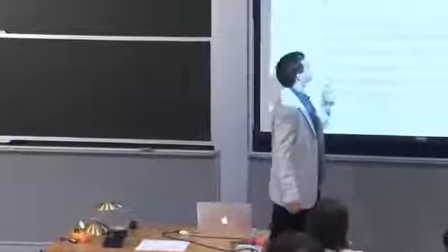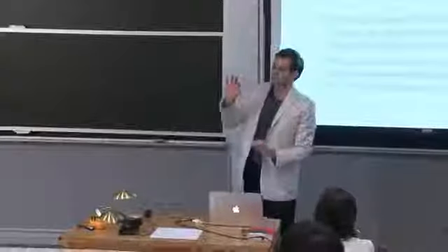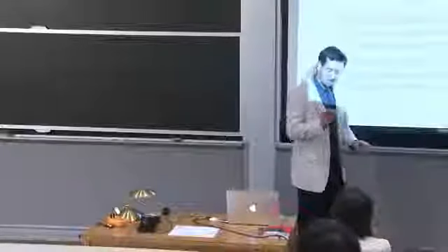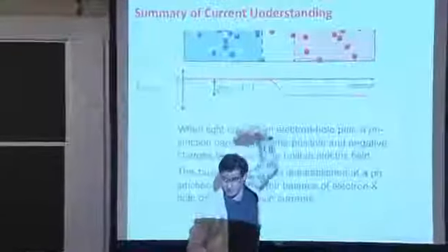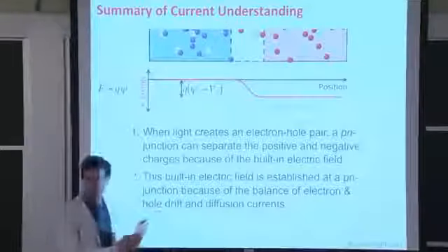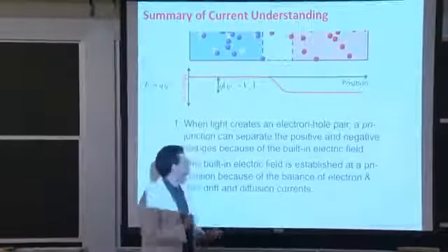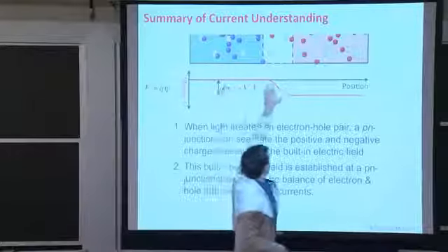For very small light intensities, such that you can think of that photogenerated carrier as a perturbation to the system, not fundamentally altering the energy levels yet. It does eventually happen. But if you have, say, one photon coming into your material, exciting an electron over here, that electron can move down, can be swept out of the device because of that built-in electric field. Again, assuming that we have a very small impact on the electrostatics of our system, maybe one single electron is not going to affect much because we have 10 to the 23 or so atoms per cubic centimeter. We have a very small perturbation to our system. That charge carrier will be swept out very quickly.